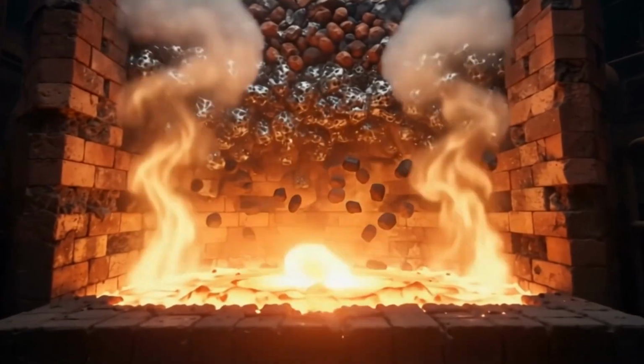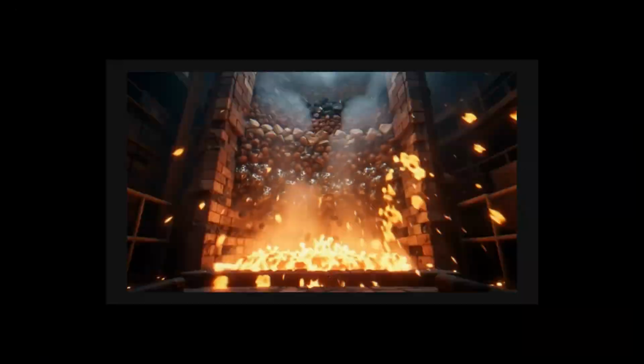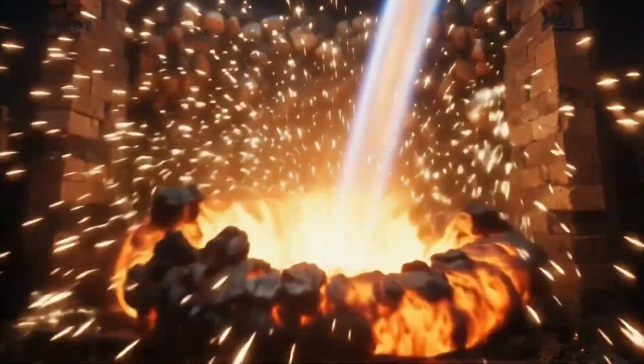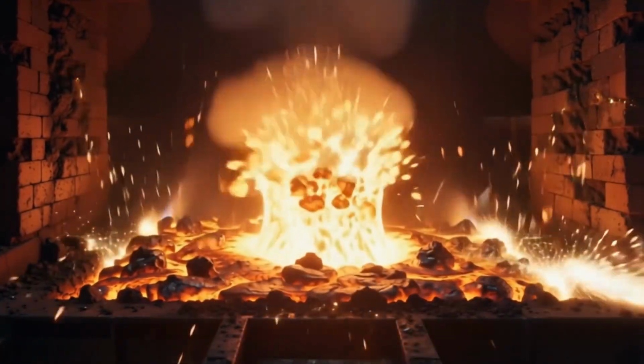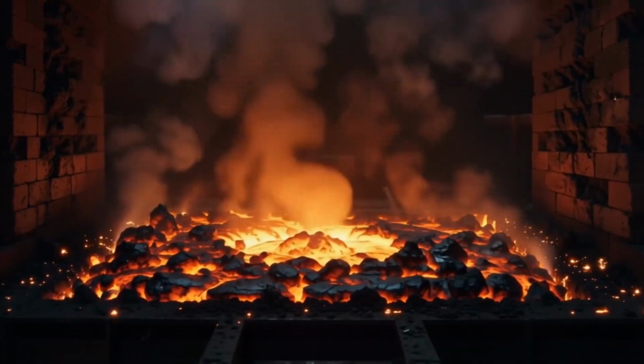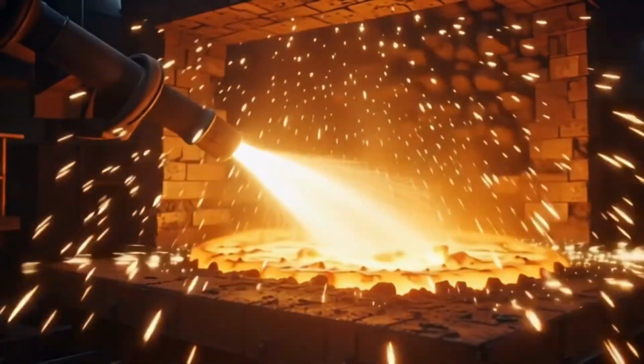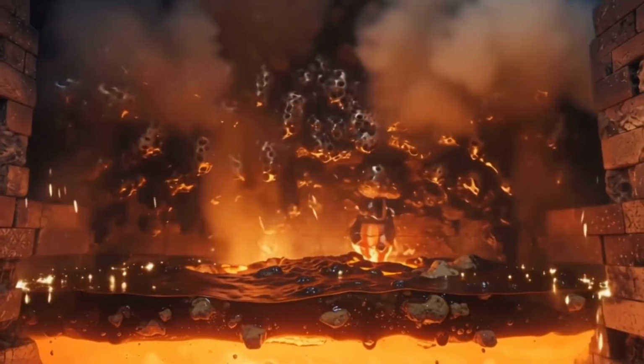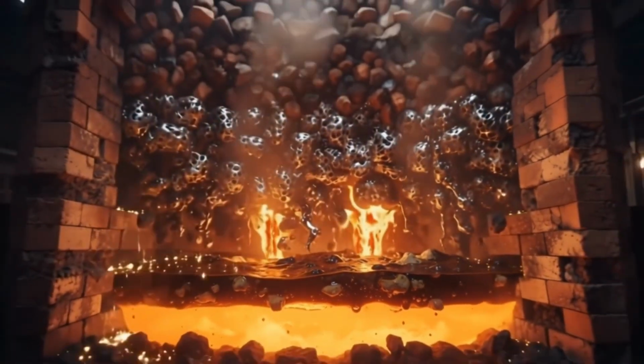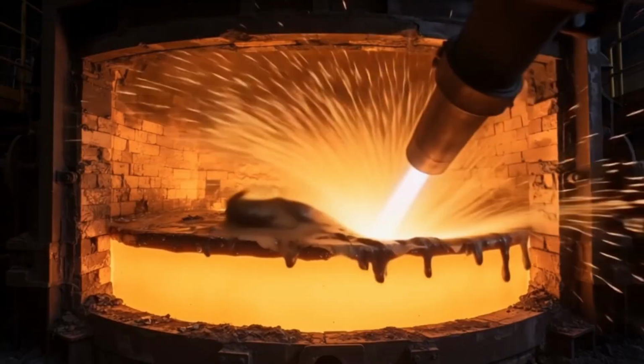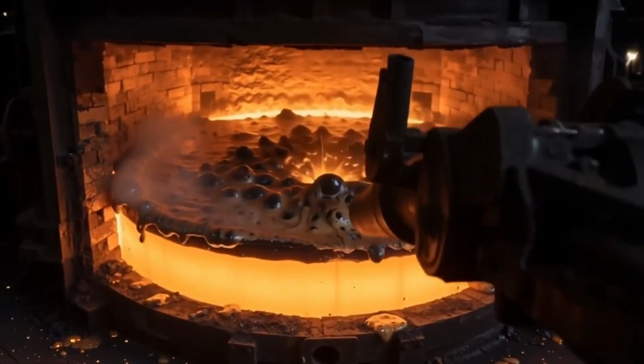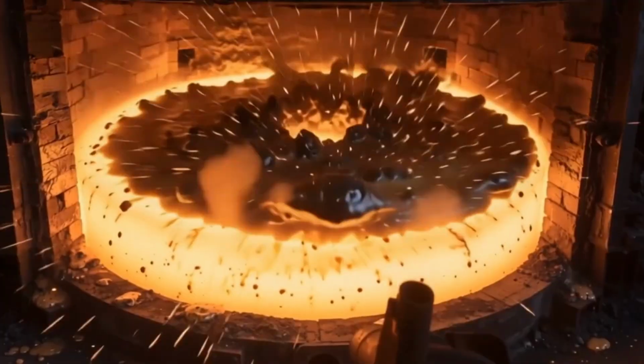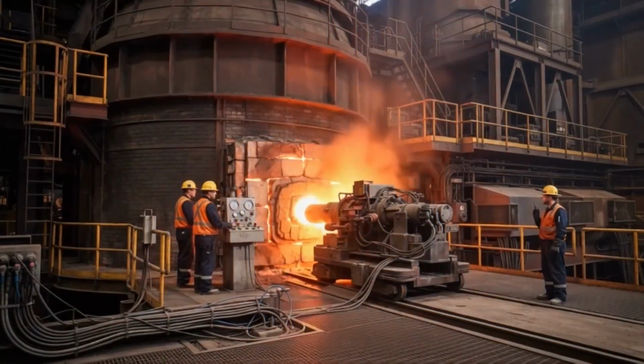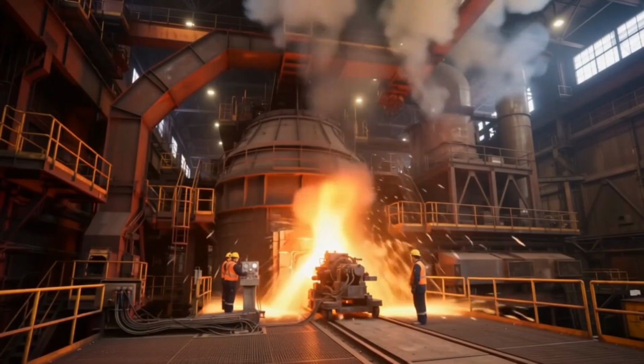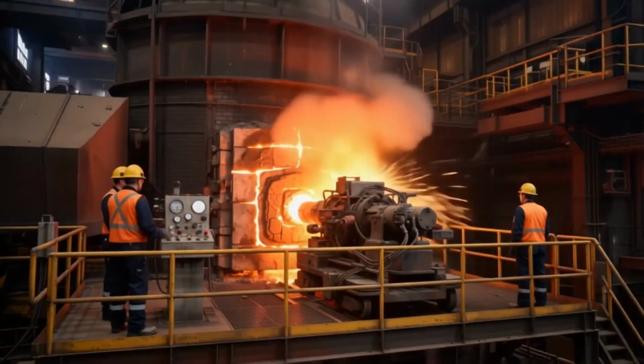Then the oxygen hits, and the chemistry changes instantly. It reacts violently with carbon and other dissolved elements. Carbon combines with oxygen and leaves the bath as gas, dramatically changing the composition of the metal. As impurities oxidize, they combine with fluxes to form a foamy slag that rises above the steel. Carbon, silicon, manganese, and other impurities are being driven out of the molten metal.